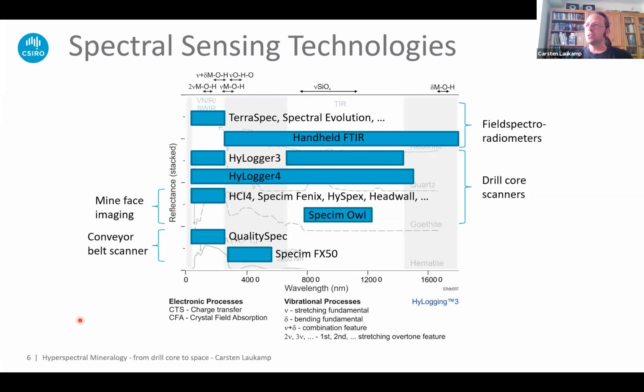Let's have a look at different technologies that are commercially available. So I just overlaid here these reflectance spectra of these 4 different minerals. Field spectrometers you maybe had a chance to use already, or you heard of the TerraSpec and FieldSpec from Malvern Panalytical, or Spectral Evolution field spectrometers. They mainly cover visible near and short-wave infrared. There is a handheld spectrometer from Agilent, a handheld FTIR that covers the whole mid-wave, thermal and even into the far infrared, which is a pretty cool tool that we are using quite a lot now, especially for lithium. The HyLogger 3, that is part of the National Virtual Core Library, collects visible near, shortwave and thermal infrared reflectance spectra. There will be, hopefully soon, by the end of June next year, a HyLogger 4 that also collects mid-wave infrared reflectance spectra.